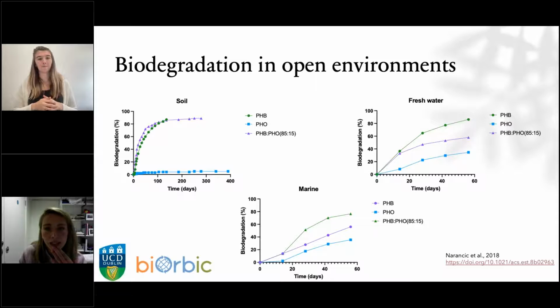But then when we tested in a big study different materials, including our short chain length PHA polyhydroxybutyrate and a representative of a medium chain length polyhydroxyoctanoate, we tested their biodegradability in different environments. So we just extracted the polymer and we simulated the environments. And you can see here their behavior in soil. Over 300 days, we were looking at biodegradation, and polyhydroxybutyrate, represented in green here, completely degrades within 120 days. The mixture of the two polymers behaves similar to PHB. However, PHO, when it's just left like that in soil, looks like it's not really degrading well.